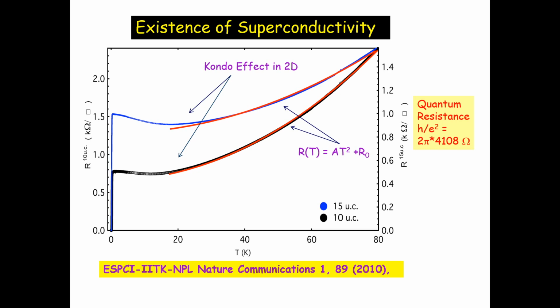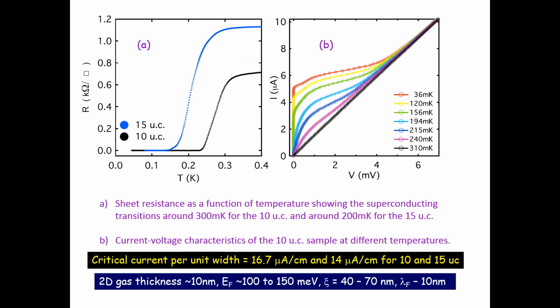Now, if we expand this portion, you see very clear signs of robust superconductivity, and also there is a well-defined critical current density. This work was done about 5 years ago, and we could infer the critical field and all that from this. These are the critical current densities, and the thickness of this 2D gas is roughly about 10 nanometers. The Fermi energy is from 100 to 150 millielectron volt. This is the coherence length, from 40 to about 70 nanometers, and this is the Fermi length, about 10 nanometers.